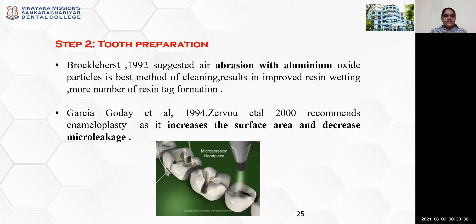In step 2, tooth preparation: Brockleherst in 1992 suggested that air abrasion with aluminium oxide particles is the best method of cleaning, as it results in improved resin wetting and a greater number of resin tag formations.